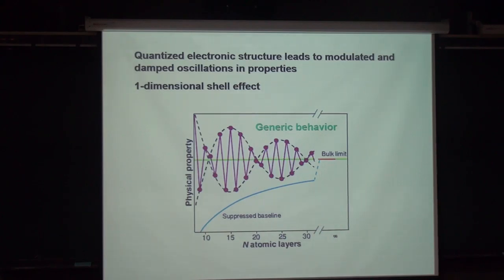However, the thickness is not a continuous variable, because when you have 10 layers, you cannot have 10.1 or 10.2 layers. So it's only 10 and 11. So there's a natural periodicity associated with atomic layer thickness. And so you have two periods in here. One is atomic layer thickness, and the other one is the oscillations associated with the electronic structure. And the two periods are not necessarily commensurate, and in general they are not. And you get this beating effect, so generally speaking, you get this beating pattern.